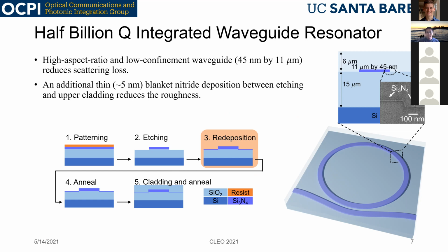Oh, I see another question on annealing of the nitride. I have to check, but I think it's like 1200 degrees, and for how long? I think it's like 7 hours. 7 hours, 6 hours. Yeah, 7. I believe it's 7 hours.